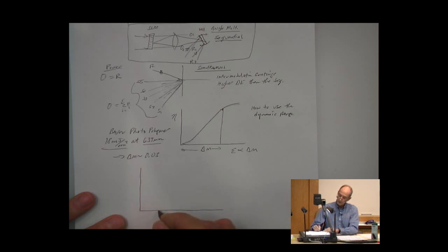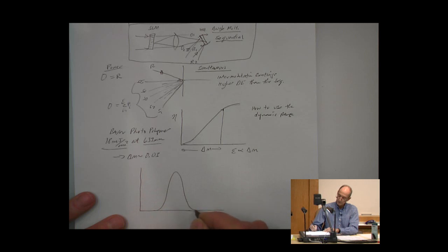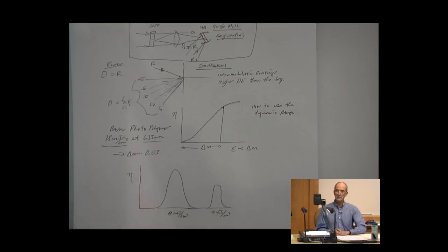if you did 9 and 9, the first grating that you would make may have an efficiency like this, and the second grating will have an efficiency somewhat lower than that. So if we did 9 millijoules per centimeter squared and 9 millijoules per centimeter squared, we'll see that we actually have a non-uniformity in the resulting diffraction efficiencies.